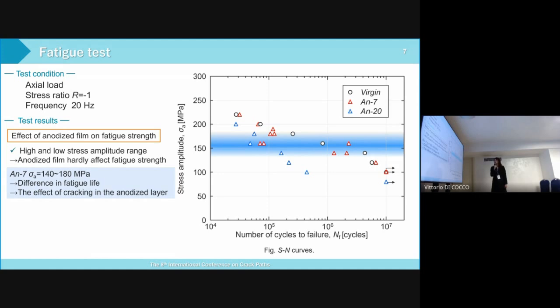First, bare and AN7 were compared to investigate the effect of anodized film on fatigue strength. As a result, anodized film hardly affects fatigue strength in the high and low stress amplitude ranges. On the other hand, in the blue area, the fatigue life in AN7 showed variation. This result is consistent with the critical stress at which cracking occurred in the anodized film.